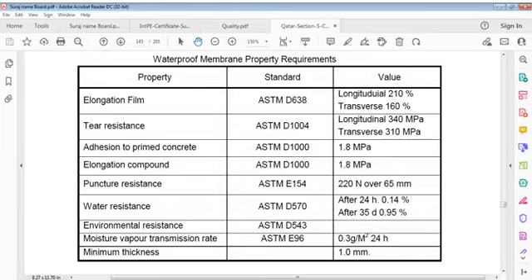Puncture resistance, ASTM E154, is 220 Newton over 65 mm. Water resistance, ASTM D570: after 24 hours 0.14%, after 35 days 0.95%. Water resistance.